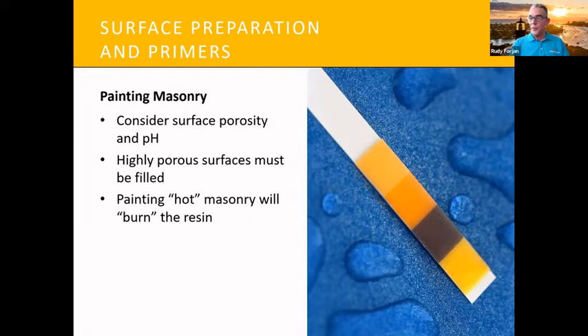Also, the most important part, and Carmelo is going to go into this a little bit later on, is trying to keep the water out of the concrete or out of masonry. That really is what causes the most amount of damage to the masonry itself, because you can reactivate the alkali within that concrete or masonry, and it can cause the paint to burn off and to lose adhesion. But most importantly, in these building structures, as Carmelo will get into, water getting in there will cause a lot of the rusting and issues with the steel in the concrete, and that's where you're going to get into a lot of repairs and so forth.